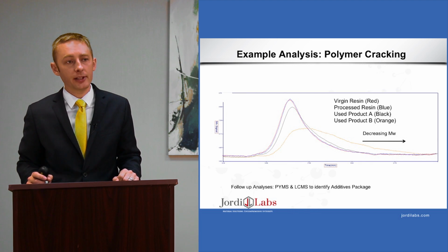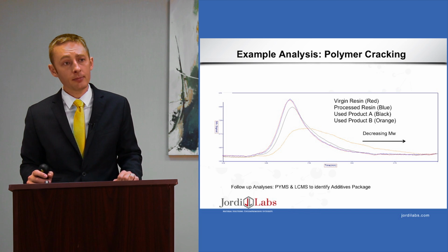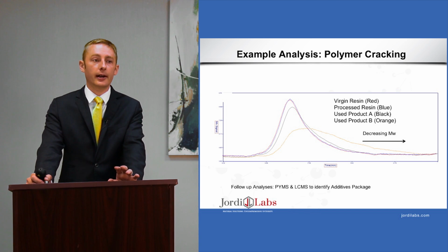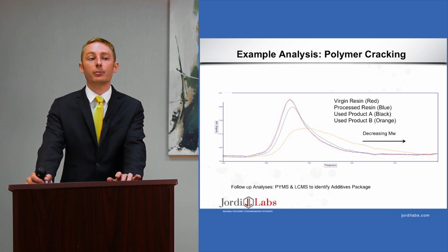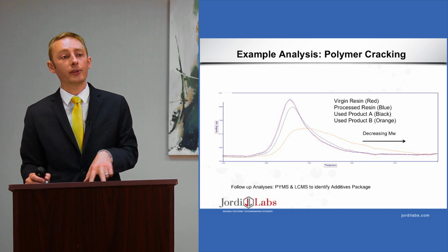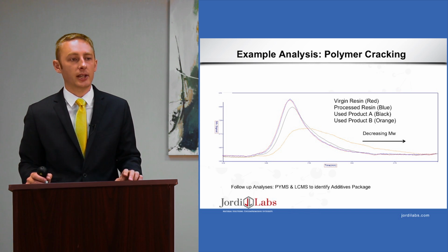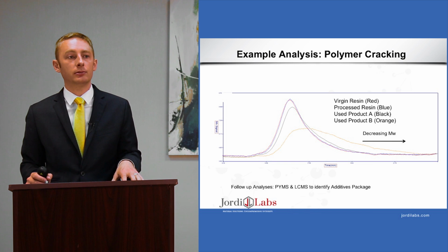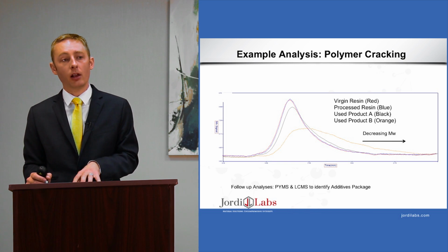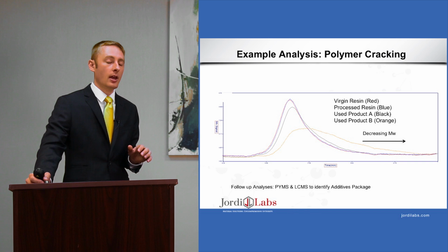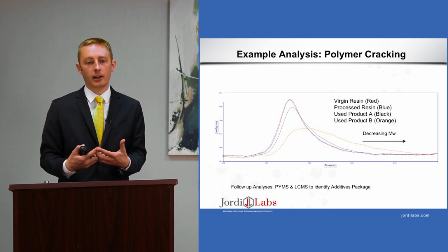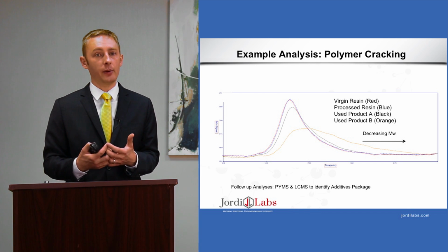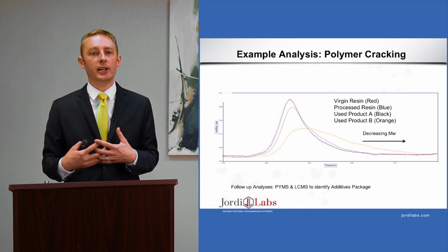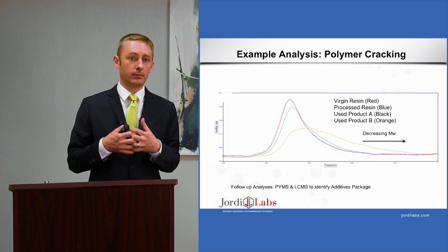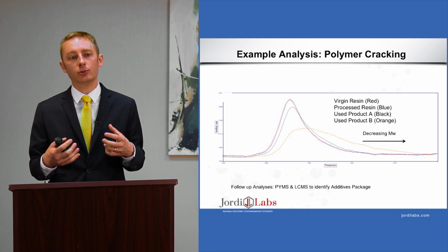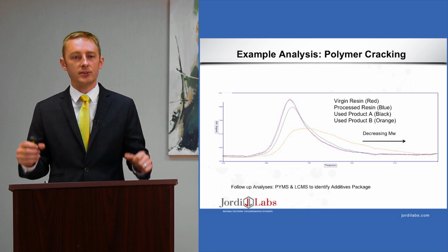And so this right here is a GPC chromatogram where we took a sample of the virgin resin, a sample of the processed resin, as well as two of the used products. They were both used in different use cases. And we were able to determine the molecular weight of the polymer in each case. And that's important because cracking is typically caused by decreased molecular weight. The long polymer chains end up reinforcing the final part, and you're able to have a more resistant material.